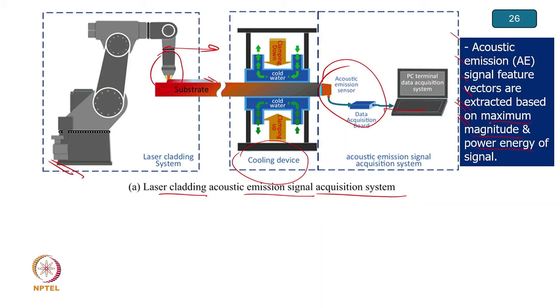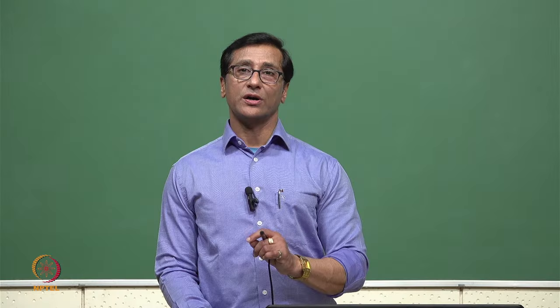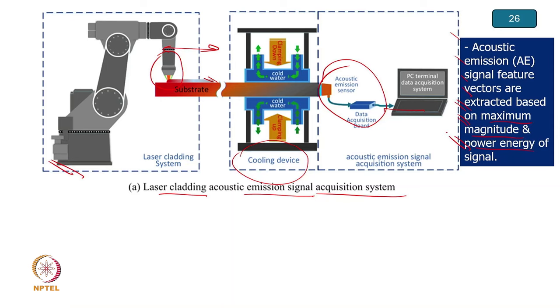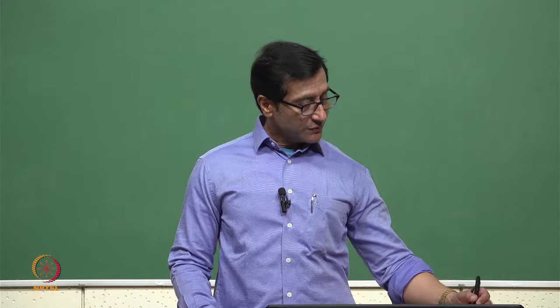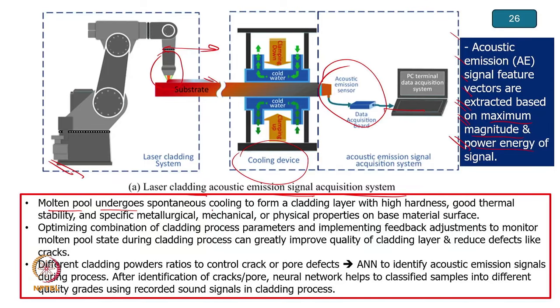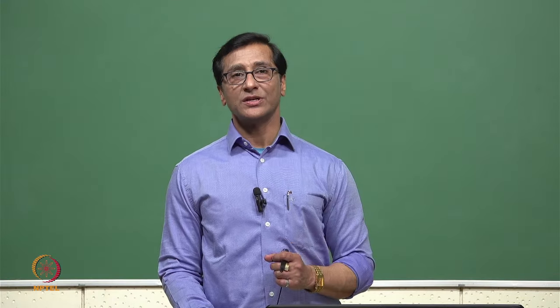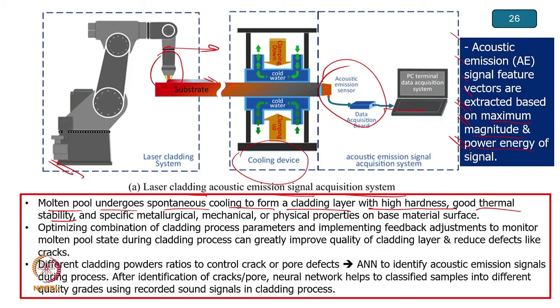So there are two things. One is the amplitude, which we have shown in an earlier relation, A is equal to A0 or maybe A(t). And then power energy is basically the integration of A squared. So that can be done in this manner. In this case, a molten pool undergoes spontaneous cooling to form a cladding layer with high hardness and good thermal stability. This is what I mentioned: because there is a change in the thermal coefficient, we require immediate cooling. If there is immediate cooling, then we will get good thermal stability, and then the mechanical properties and physical properties we want can be tuned.